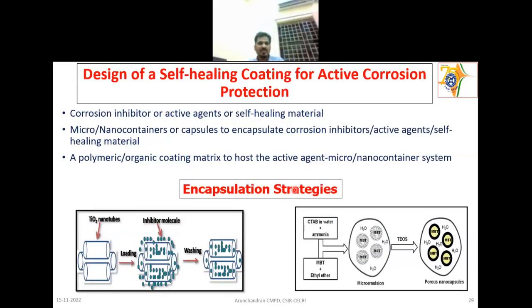This is how you design a self-healing coating for active corrosion protection. So what are the things you need for that? One is you need to first find a corrosion inhibitor, that is an active agent or a self-healing material. This can be an inhibitor or a self-healing material like tung oil or linseed oil. There are some publications on linseed oil and tung oil. They get encapsulated in urea formaldehyde microcapsules. Then you need micro or nano containers or capsules to encapsulate these inhibitors or active agents.